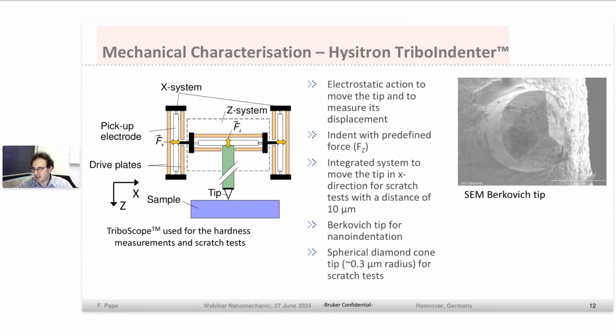And we can see here the tip, which is mounted on a pickup electrode, which is placed between two plates, allowing us by electrostatic force to displace the tip into the substrate. And by a change in capacitance, we can measure the displacement itself. So it's very precise to investigate the response of our material to the applied load. And by a so-called XY system, the middle system can also be moved along the surface, allowing us to perform a scratch test. On the right, there's a SEM image of a so-called Berkovich tip, which is commonly used for hardness measurements.